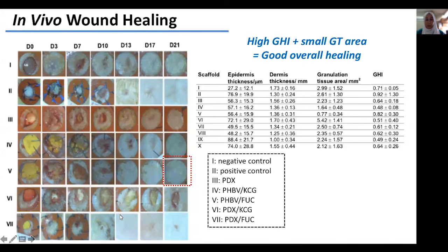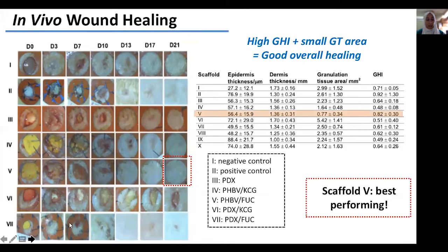Therefore, if we look closely at the table on the right-hand side, we note that scaffold 5 led to the lowest granulation tissue area and the highest global healing index, which indicates that this scaffold led to the best performance. And scaffold 5, if we look at the table here, corresponded to PHBV fucoidan. Therefore, the scaffold contained fucoidan in combination with the piezoelectric polymer, which confirms our hypothesis that fucoidan, in combination with a piezoelectric polymer, leads to better or accelerated wound closure.